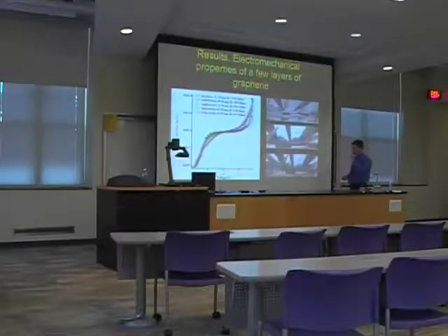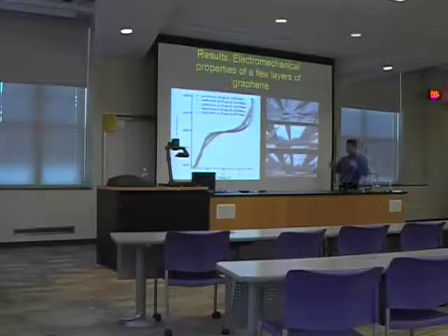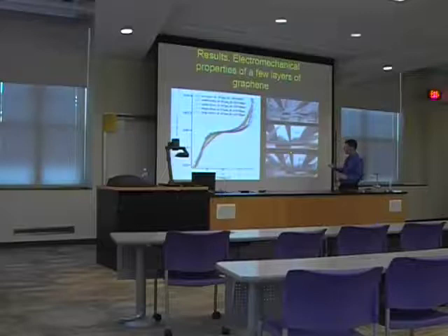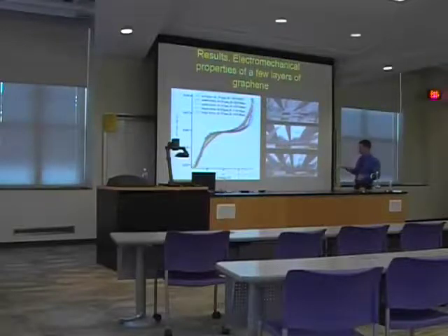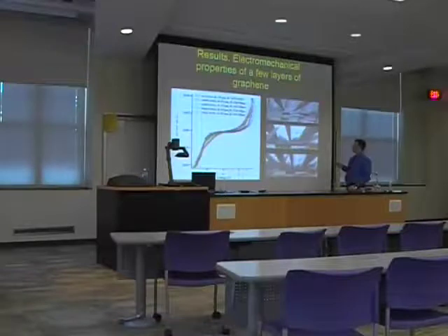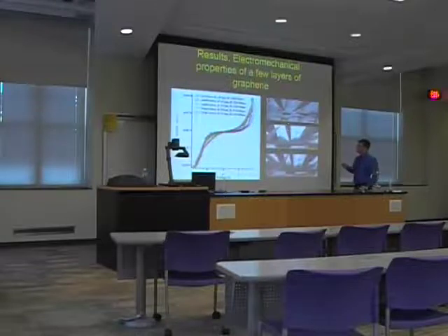And this is another experiment, a pretty cool one. I like it a lot. So we have 3 probes. It's really hard to target a small piece of graphene, like 10 microns, with 3 probes at one point. So this is not monolayer, it's like 7 layers probably. So we attach electrodes, and it's suspended between the trenches. We attach electrodes to it, and then push it with a 3rd electrode in the middle.